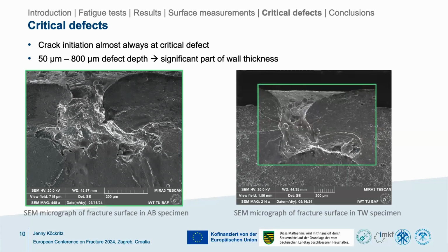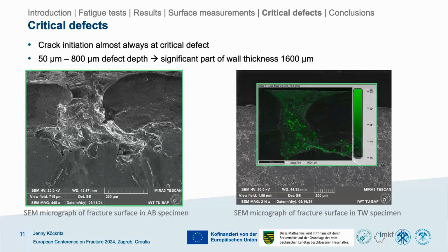And we also did some EDX measurements of these defects, and we can observe huge oxygen concentration in these. So they very likely originate from the printing, because this specific alloy, this 2139 alloy, needs very high energy densities for printing. At the same time, we have a very thin-walled piece that doesn't have a lot of support structures, so heat isn't dissipated very well. In combination of the alloy with the geometry, that means we have a higher chance of printing errors to occur here.